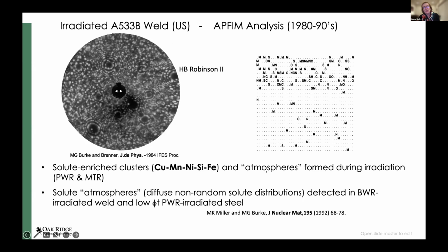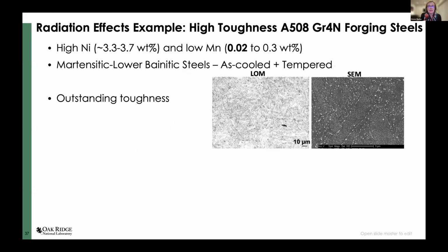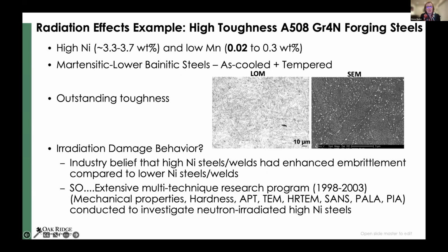But anyway, it turns out that there were solute enriched clusters that were detected via atom probe analysis. And these solute atmospheres, which were diffuse non-random distributions of solute, were also prevalent in irradiated steels, but not present in non-irradiated steels. Looking at some other materials, bainitic and tempered martensitic steels, great toughness. I wanted to give a plug: light optical metallography is still important, along with scanning electron microscopy.